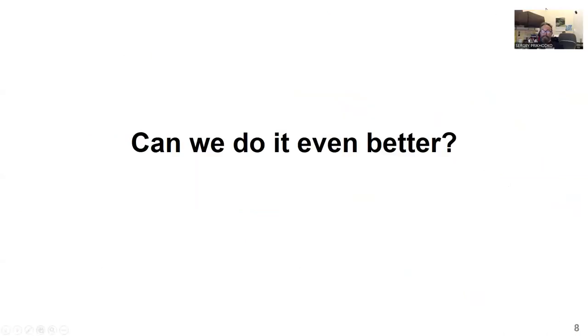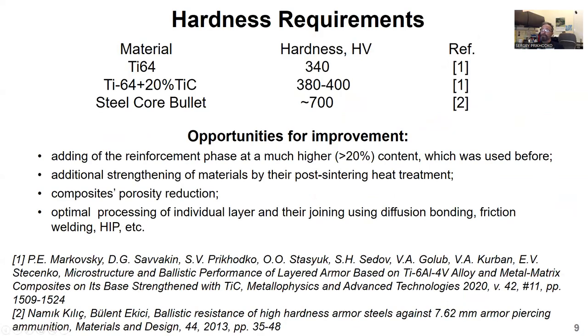Well, can we do it even better? In the second part of my talk, I'll try to give the answer, and it is rather optimistic. The real steel bullet hardness is close to 700 HV. So we need hardness close to this for effective protection. The most logical way to increase the hardness of composite is to add more reinforcement compared to what was used before, say higher than 20%. Additional hardness raise can be achieved through the base alloy structure modification by using a specific heat treatment.